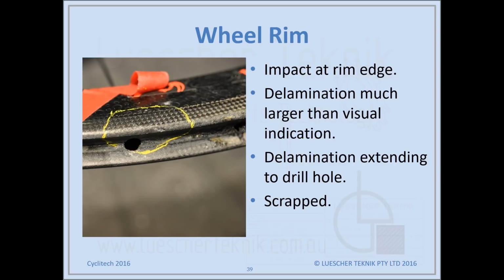This is a wheel rim, a tubular rim, but it's had an impact, and you can see the impact right here. When we scanned it, the delamination, as marked in yellow, is much more significant than what the impact looked like visually. It goes all the way to the spoke access hole and past the brake track. So in this case, it was scrapped. In other cases where the rim damage is limited to what you'd see visually, you'd be able to repair that, but the delamination is the main damage here.